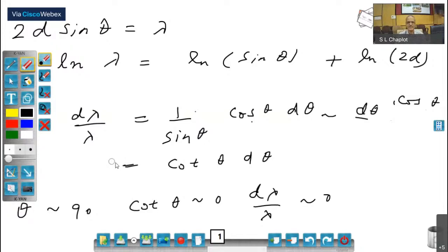The reason we use different ones is that they have a somewhat different scattering length, but more important, the d spacings are different in those crystals, and therefore you can get the same wavelength at different values of the Bragg angle, and depending on the Bragg angle, your resolutions are different. So, for example, copper gives a much better resolution than graphite. So that's the way we select the monochromators.